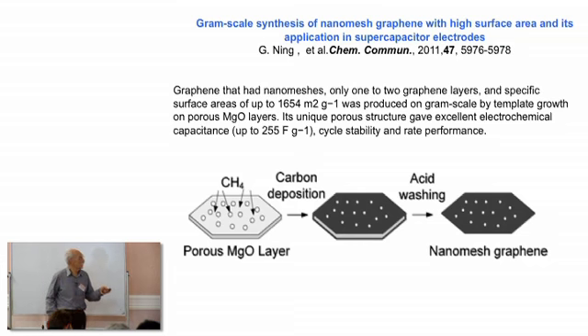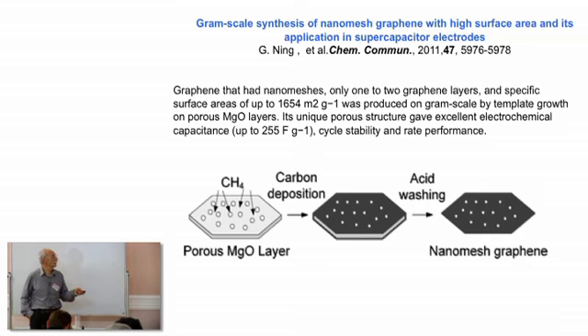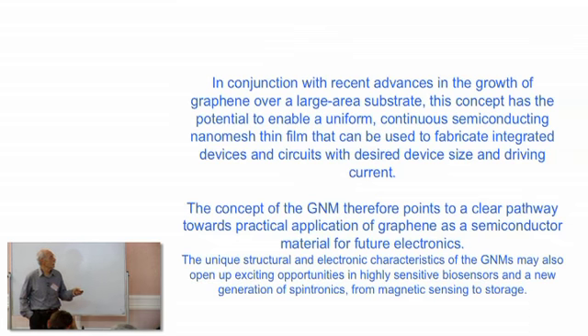Another way is possible to prepare it using some organic molecule put on the carbon surface, and then etching and washing removes it, giving a prepared nanomesh of graphene. It can also be used with a porous magnesium oxide layer or aluminum oxide materials, nanoporous materials, and so on.